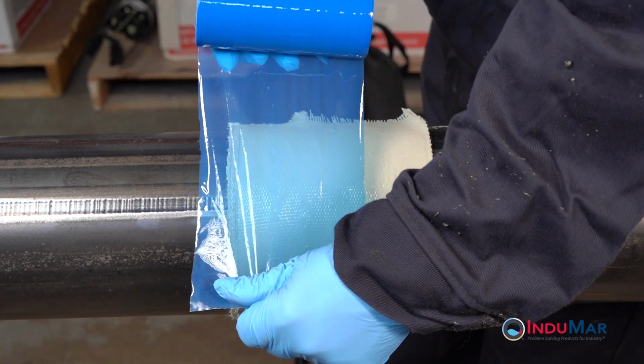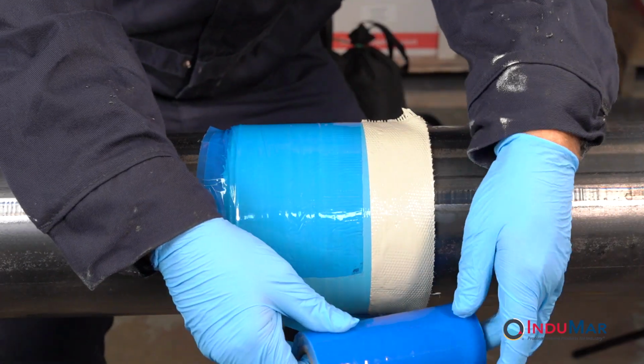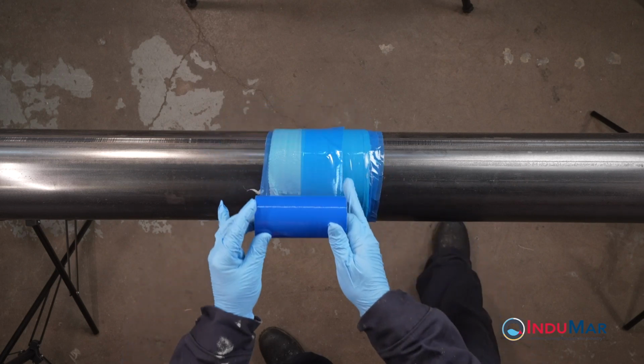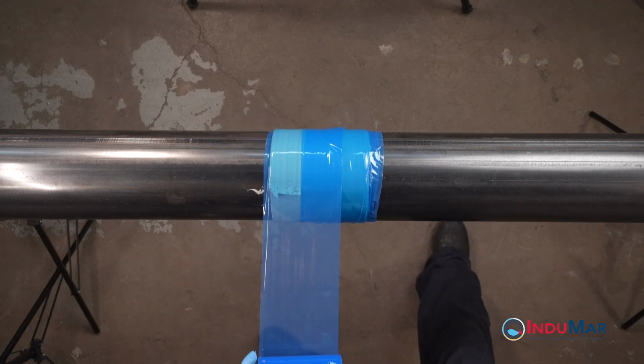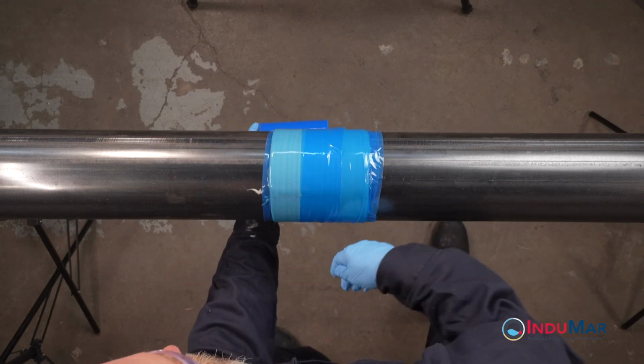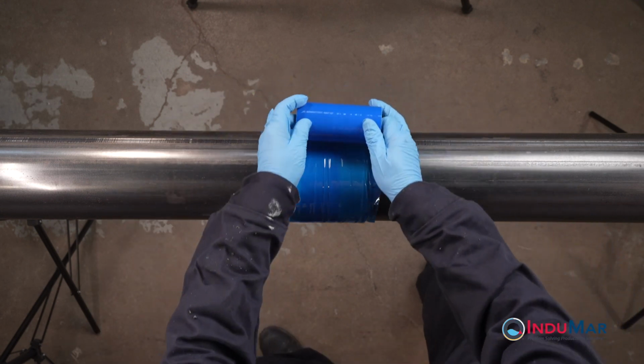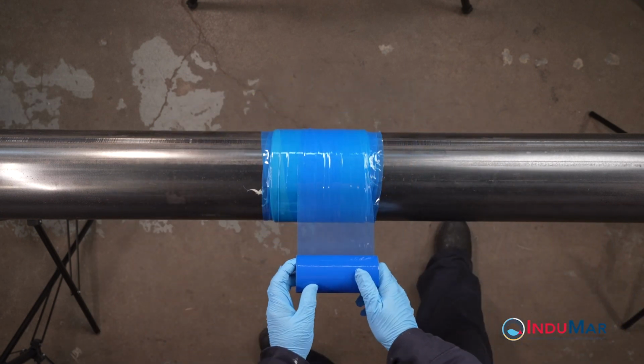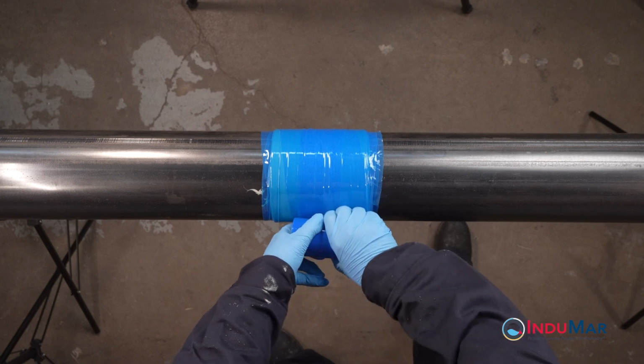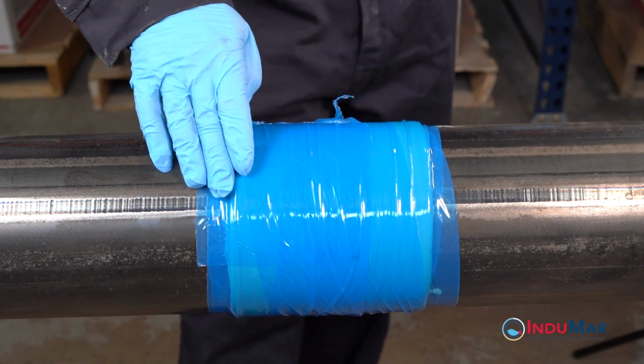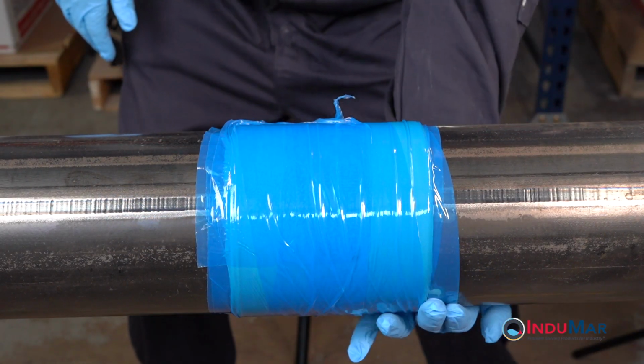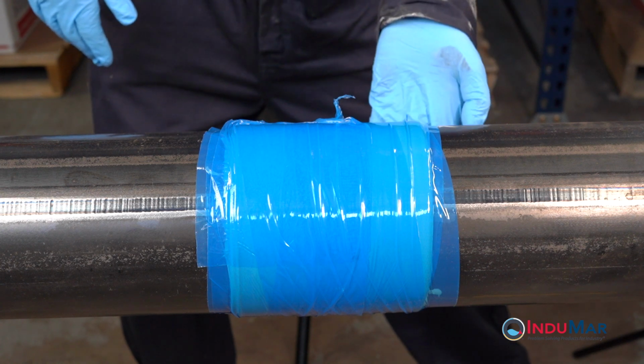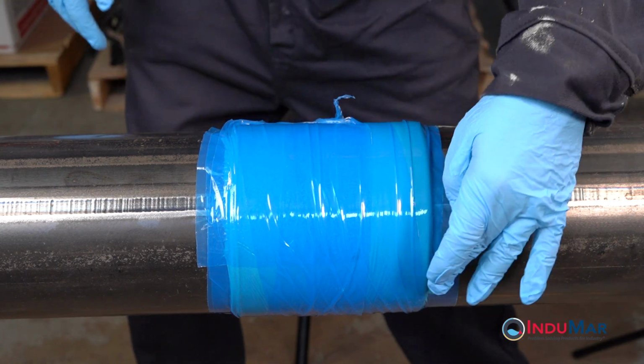To complete the application, apply compression film tightly over the composite wrap. Through a combination of overlapping and spiraling, look to apply about 4 layers of film in all places. As with the composite wrap, it is best to keep the roll of compression film close to the pipe when applying. Once the film is in place, massage the resin into the end sections of the fiberglass to achieve smooth transitions to the pipe. After the epoxy has fully cured, the compression film can be removed.